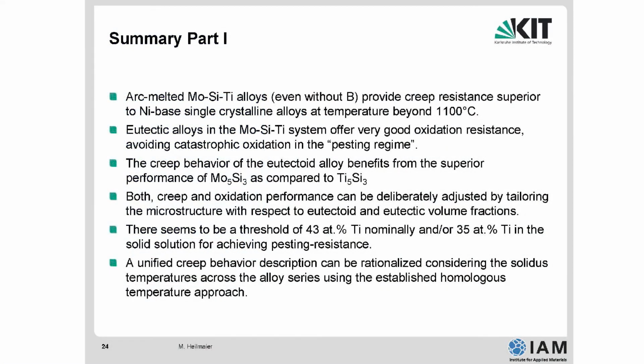The creep behavior of the eutectoid alloy benefits from the superior performance of Mo5Si3 phase as compared to Ti5Si3. And both creep and oxidation resistance can be deliberately adjusted depending on the alloy composition if I walk along the transformation line between eutectic decomposition and eutectoid decomposition. There seems to be a threshold, I didn't show this in detail, of 43 atomic percent nominally or 35 atomic percent in the solid solution for achieving pest resistance. You need a minimum titanium content to avoid pesting. That's what it says. And finally, you can describe the creep behavior by a unique and simple approach which relates the actual creep testing temperature to the melting point of the alloys. And this is called the so-called homologous temperature approach.